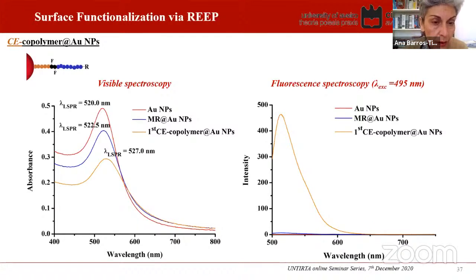So as we anchored the macro Raft onto the gold nanoparticles, we have a small change, from 520 to 522.5 nanometers in the absorbance maximum. But once we anchored this fluorophore, and so carried out a chain extension of the macro Raft, this shift of the plasma resonance maximum really changed to 527.